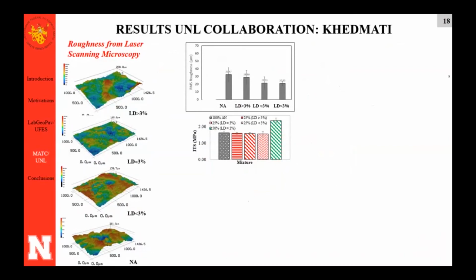Now going to the analysis of the roughness by using the laser scanning, you can see here the natural aggregate has a higher roughness than the slags in general, and the level of expansion again didn't vary the roughness much. But one thing was interesting. The higher the roughness, people say, the better the mechanical adhesion between binder and aggregate. But why, when I have more slag, do I have a higher indirect tensile strength? Indirect tensile strength is an indirect way to measure how these components are working together in terms of adhesion.